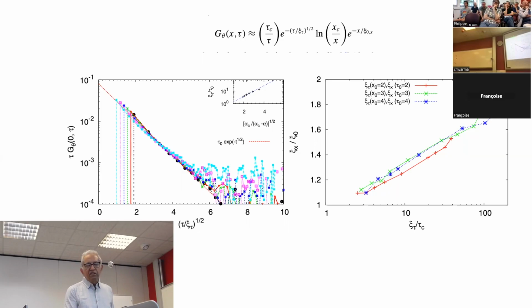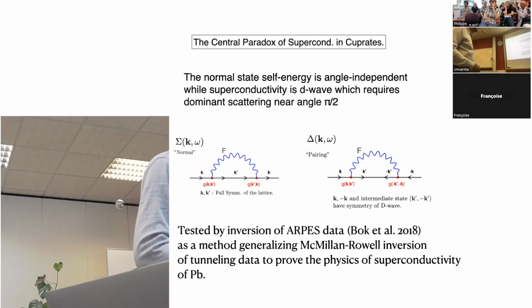Simultaneously, we can look at the spatial correlation length for a fixed time, and this is on a linear scale, and this is on a log scale. So to only this accuracy, we can say that the spatial correlation length is going as logarithm of the temporal correlation length. Okay, that result can be derived analytically by RG as well. So the spatial correlation length goes as log of the temporal correlation length. It is effectively, not exactly, but effectively saying the so-called dynamical critical exponent is diverging. It's going to infinity. That's important to rectify the phenomenology that we had proposed.